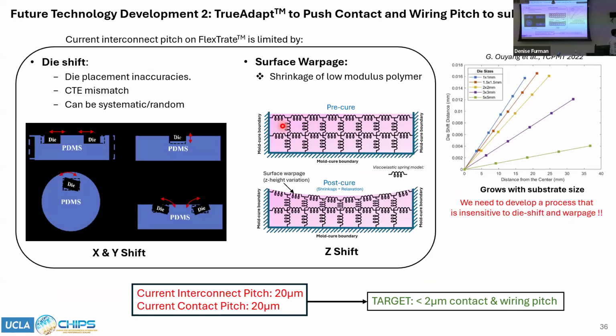So if you look at the current interconnect pitch on FlexTrate, it is 20 microns, and the reason we can't push it further is because it's very difficult to do lithography to define the interconnects. And the reason this happens is because there are two important issues. One is the die shift, and the other one is the surface warpage. So die shift occurs because when you're placing the dies originally on the tape, as I showed before, sometimes there could be some misalignment during the assembly process itself.